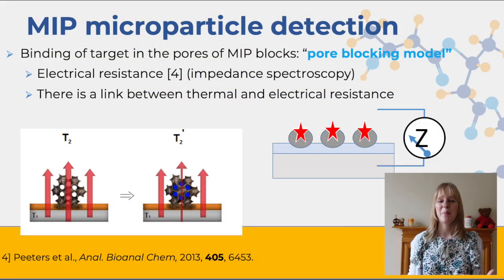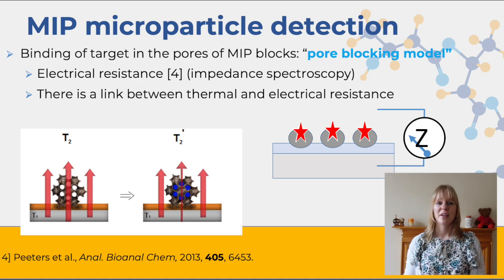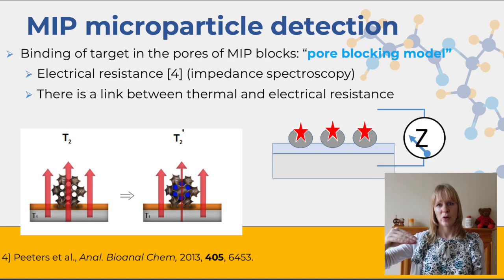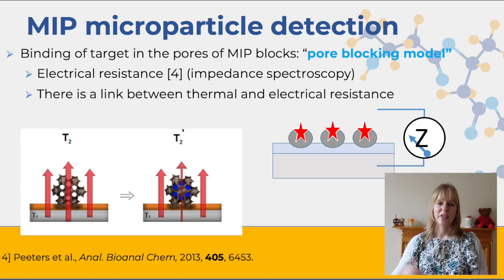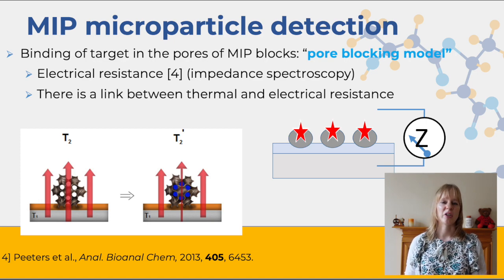So when I started my PhD, I started working with microparticles. I developed particles, and here you can see that these MIPs have a porous structure. And we found out that as soon as there's some binding in these pores, you block the electrical resistance. Because electricity will always find the easiest way to go through things, and when that path is blocked, you actually see that the resistance increases. And the electrical resistance, we measure with impedance spectroscopy.